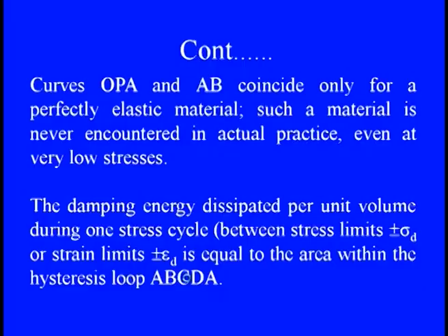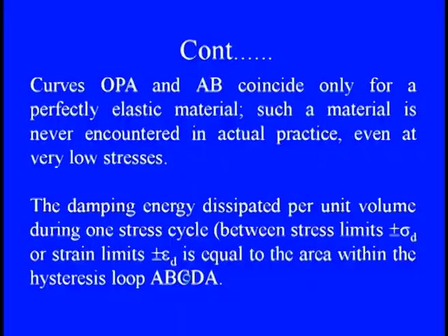Now, the curve I am going to show you has two main features. Say O-P-A and A-B coincide, then that means when there are no hysteresis loops being formed, it is a perfectly elastic material. This perfectly elastic material allows the energy to be absorbed and an equal amount of energy to be released during loading and unloading conditions. But this behavior cannot be anticipated in real world problems, even when we have low stressed cycles, because whenever things are happening, there is a clear deviation in the path of absorption and the released feature of energy.